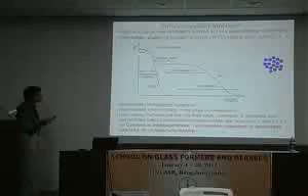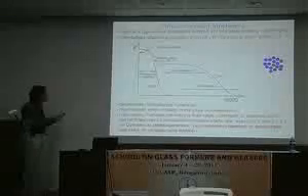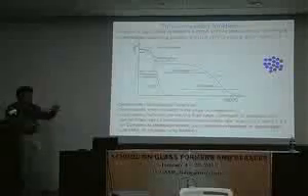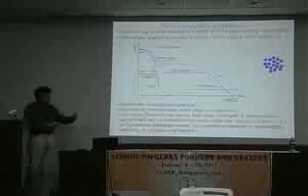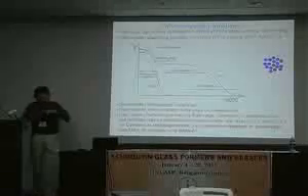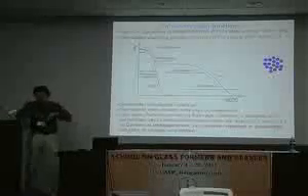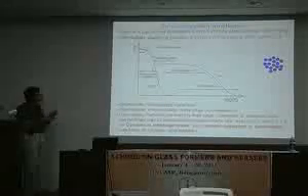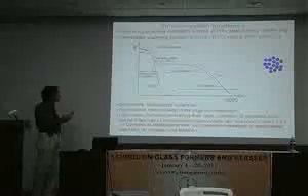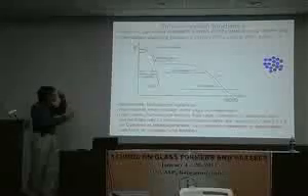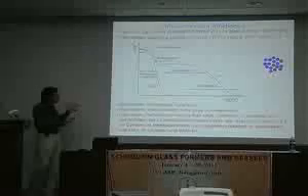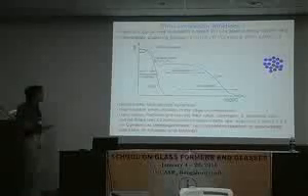So typically what's happening is if you are at high temperatures, you have at short times something that is usually called a ballistic regime, that is to say a quadratic dependence of the time correlation function. This is again just because the particles are Newtonian, they displace themselves in a linear way, and so you can make a Taylor expansion of all quantities that you care about, and therefore all these quantities will have a quadratic time dependence at very short times. Then if you are at high temperature, usually you get a decay, and that is an exponential, and that is usually quite quick. It's on the order of picoseconds for an atomic system.